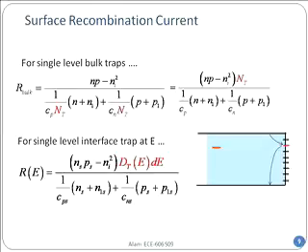Okay. Now, if I know that's the recombination for one surface state at energy E, what do I have to do in order to sum them all up? Just do an integral, because I'll just integrate over all those energy levels of the single surface states. Why do I not have double integrals, where the electron comes down once at one level, makes another stop, and then goes down? Because of what I just explained in the last slide. You are not allowed two stops going down. So it's a simple single integral over energy of that original formula, and you are done.